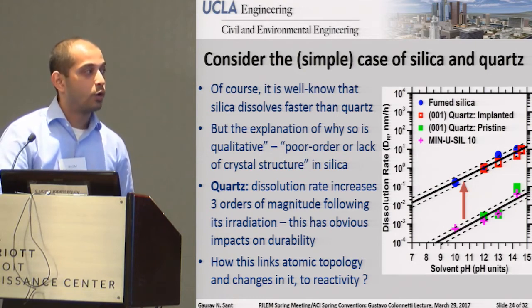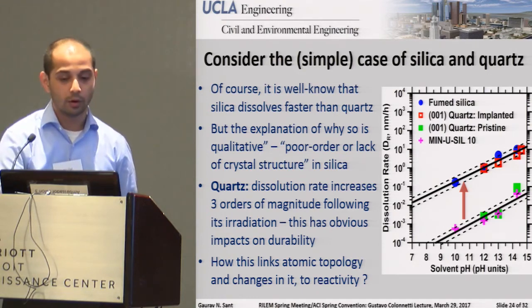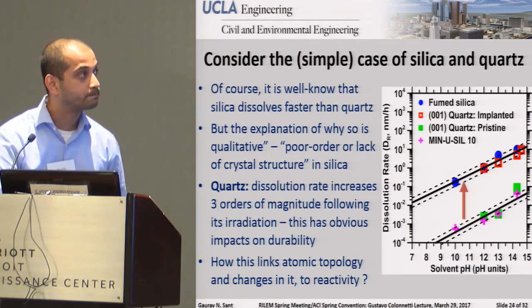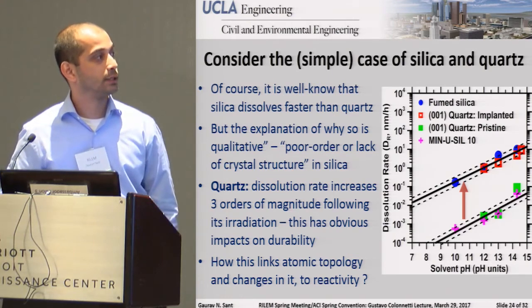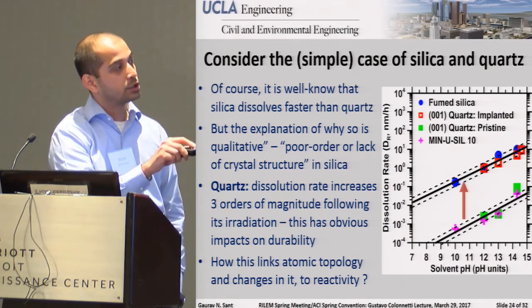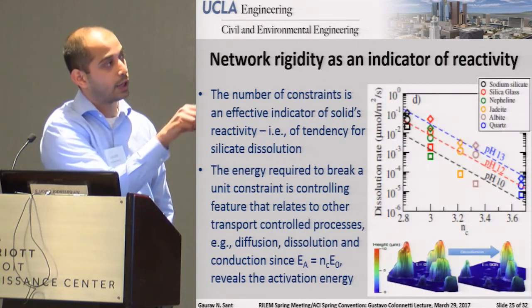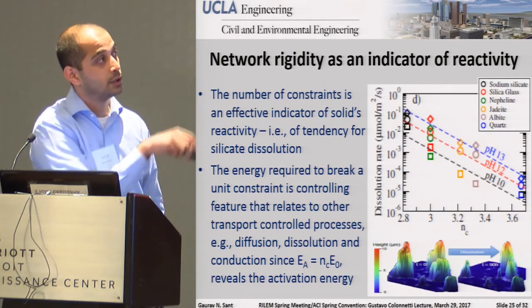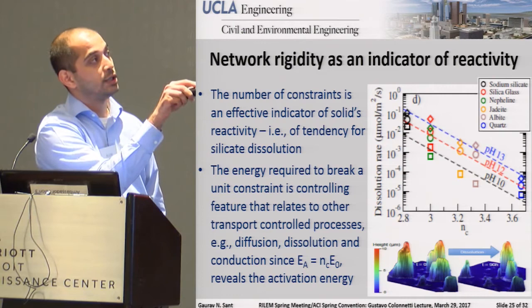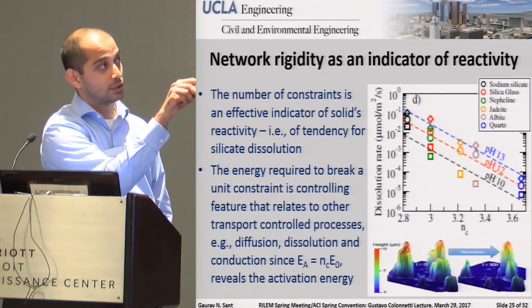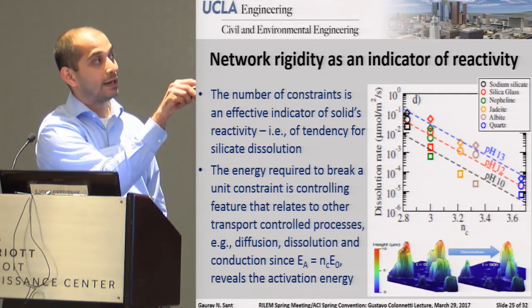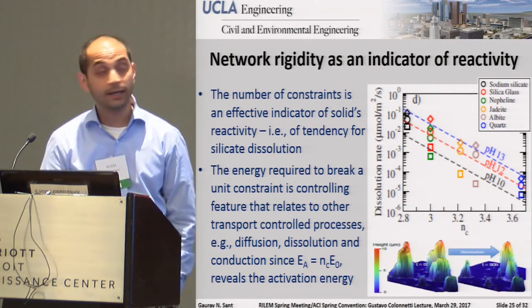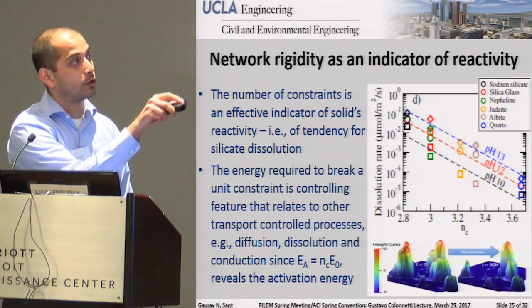So the question is, of course, how does this link to atomic topology or the number of constraints and hence to reactivity? So really the first thing that you can start with doing is you can plot the dissolution rate as a function of the number of constraints. And you're seeing this for a couple of different pH levels for quite a few different solids. So essentially things going from a sodium silicate glass to silica, to nepheline, jadeite, and albite, which are aluminosilicates. These are the glassy versions, and quartz.